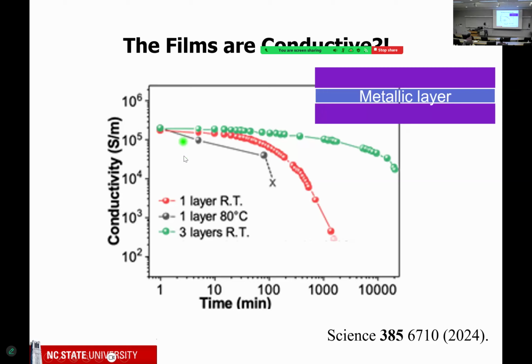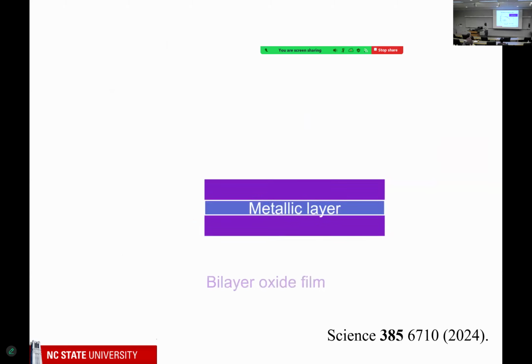But unfortunately, if you look at the red data, which is where we've printed one of these bilayers, you'll see it's conductive, and then after about a few hours, it dies. And when it dies, it starts to become even more transparent. That gray color goes away. So it means whatever sort of metallic character this bilayer film has, it goes away, it oxidizes. So we said, well, okay, what if we print 3 layers? Maybe it'll sort of protect it, and it does, which is what this green data shows, but eventually even that starts to decay. So I don't love the solution I'm going to show you, but it ended up being very interesting in a kind of an unexpected way.